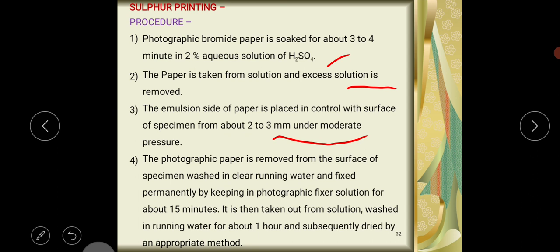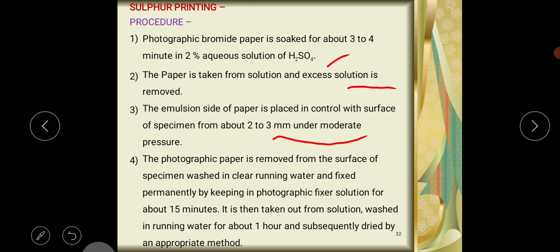Permanently by keeping in photographic fixer solution for about 15 minutes, it is then taken out from solution, washed in running water for about one hour, and subsequently dried by an appropriate method.